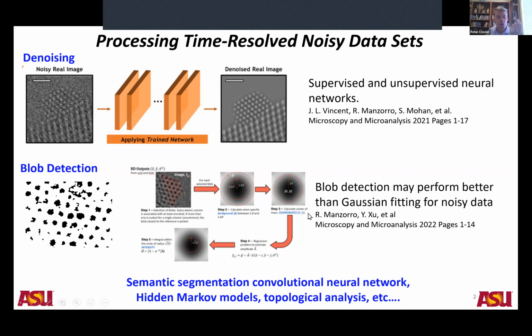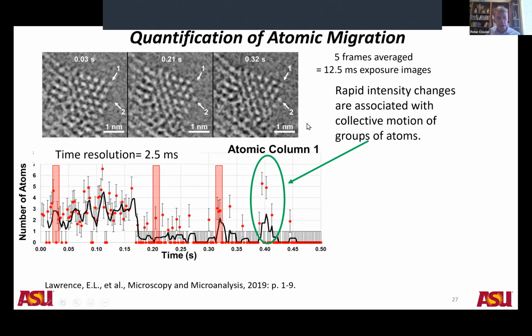Blob detection, if you want to know the positions of the atomic columns in very noisy data sets, we've actually found that this blob detection approach from computer vision seems to be more stable than Gaussian peak fitting, and we just published that a few weeks ago. And then we're using other techniques, semantic segmentation, neural networks, hidden Markov models, topological analysis, etc.